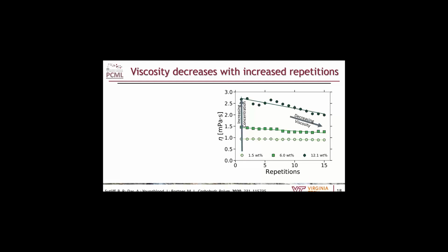But all of them decrease in viscosity as we continue to shear them with our system. In all cases, these were sheared at our highest rate, which was 800,000 reciprocal seconds, or just about. It was actually 794,000, something like that.